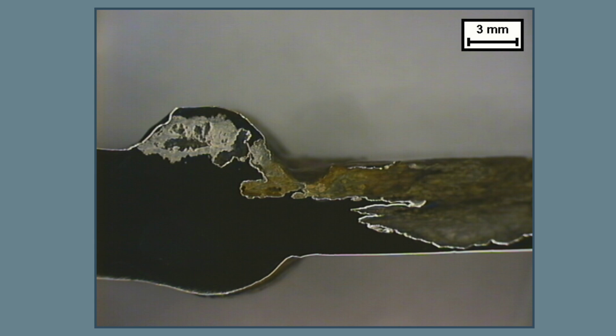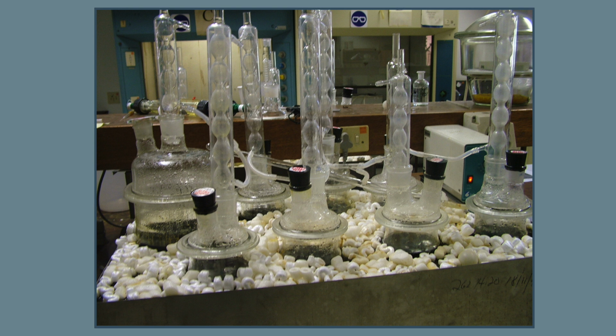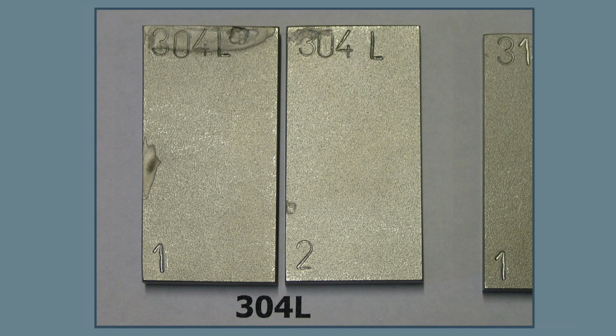But at the end of the day, we tried to do a simulated corrosion test. And I think the next slide is quite a fun one. That looks like a great scenario. Running a couple of vessels with a few alloys to try and see if we could simulate or predict the corrosion. And here we actually saw that we had a lot of settling onto the samples, although we were stirring as well from underneath. So the deposits just had a natural tendency to settle. And this is what led us to the conclusion that it was under deposit corrosion. From these corrosion tests, we actually looked at various other alloys. The vessel was actually made of, I think it was 304 stainless steel.